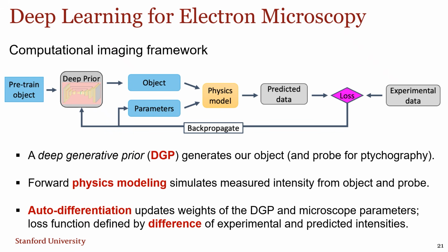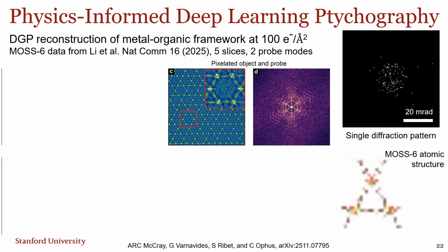So as long as you can write down the forward problem, this is a framework that you can use to solve these problems. So this is an example using data on a metal organic framework, and this material is so beam sensitive that you have to be in the tens or hundreds of electrons per angstrom squared. And the upper right is showing what one of those measurements looks like, right? It's very sparse. We only have a couple hundred or a couple thousand electrons in each pattern. And if you do a reconstruction, that's what we're showing here, this pixelated object, it's very noisy and very blurry.